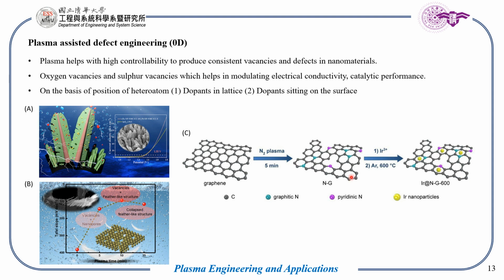Here in the first figure A, we can see work done by Liu, in which they adapted nitrogen plasma etching to create abundant and uniformly distributed defect and vacancy sites on the N-G, that is nitrogen-doped graphene, array surfaces, after which they created some defects, and these defects were further filled by iridium nanoparticles, which helped in increasing the hydrogen generation.